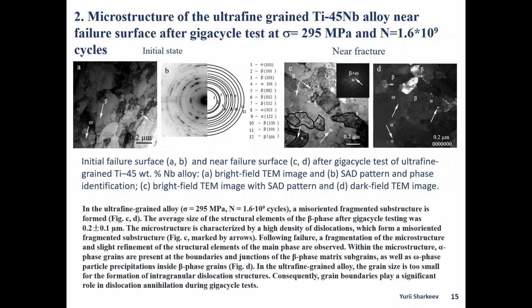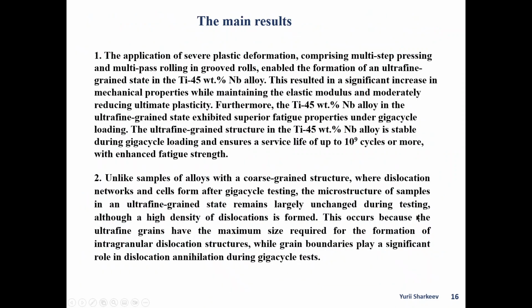Within the microstructure, alpha phase grains are present in the boundaries and junctures of the beta phase matrix subgrains, as well as omega phase particle precipitates inside beta phase grains. In the ultrafine grained alloy, the grain size is too small for the formation of intragranular dislocation structures. Consequently, grain boundaries play a significant role in dislocation annihilation during gigacycle tests. Here are the main results of the work.